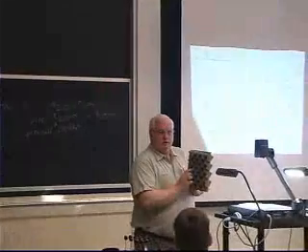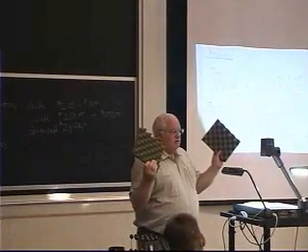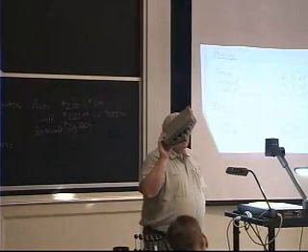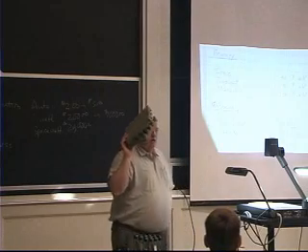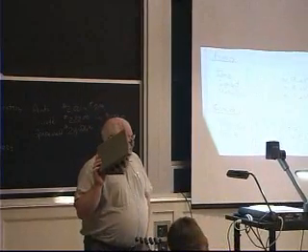And so that's what I use this for. Macroscopically, I might have something that looks very flat, and I put it back together, it looks like I got 100% area of contact, but on an atomic scale, I have something that looks like this. And I try to put it back together, and it only touches at a fraction of the spots. And we'll talk later about what fraction of those spots, but it's always less than 30%. It's typically 1% or even less.